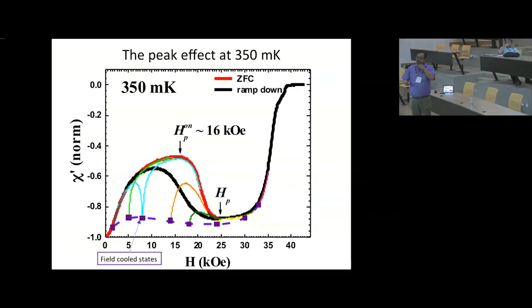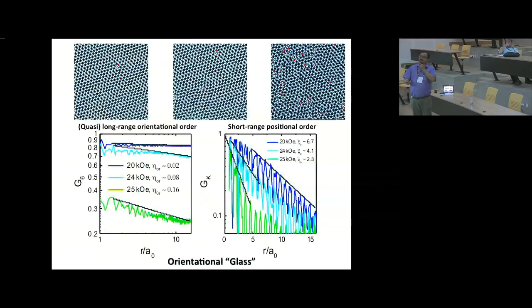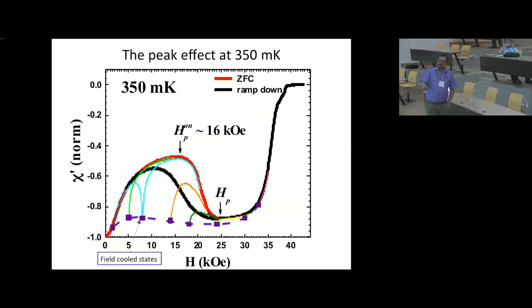Now, before I go further into this orientational glass, let me just show you that we can also access various metastable states. You see, this was the curve that I was tracking before, but here you have another set of points. What are these points? These points are the field cool points. So these are individual points where you have applied the field at a high temperature, 7 Kelvin, and then cooled the sample to 350 milli-K at this field. So these data are not acquired as a sweep like this. They are individually acquired, and that is why you have the broken line connecting them.